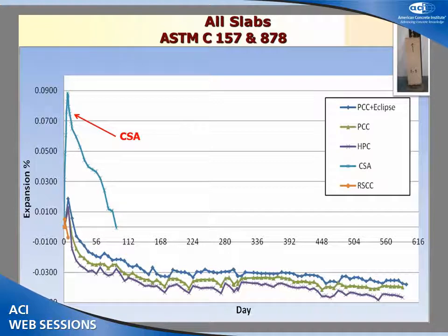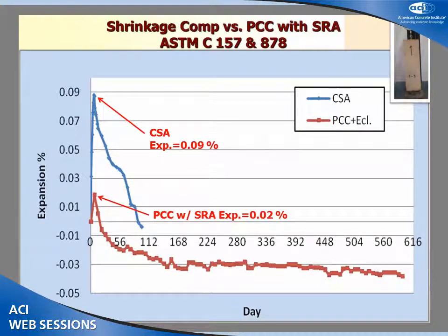I wanted to show you the expansion of calcium sulfoaluminate in the first days of curing, comparing calcium sulfoaluminate with one of the shrinkage reducing admixtures. This graph shows that the calcium sulfoaluminate has a 0.09% expansion in the first curing week, and then the shrinkage reducing admixture has 0.02%, so the calcium sulfoaluminate expansion is about 4 times greater than the shrinkage reducing admixture.